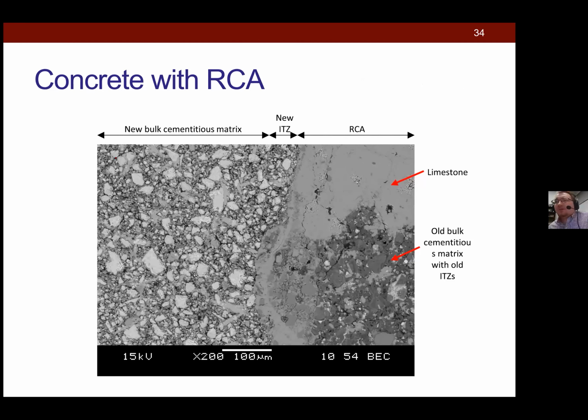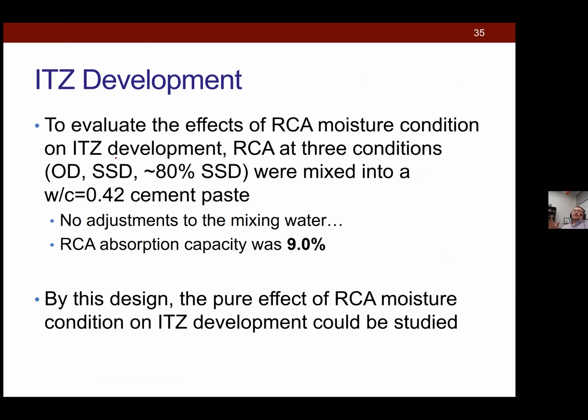So yeah, here we can see these old and new ITZs. That was one of the challenges we see with RCA. So now you can have this sort of weak plane in the old aggregate from the old ITZ, but then you can also have these weaknesses with the new ITZ. Biggest problem with RCA that I would argue is the absorption capacity. RCA will absorb a lot of water. We've looked at RCA fines that have moisture absorption anywhere from 6-7%. We looked at one even up to 12%.